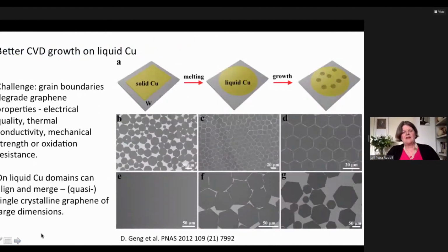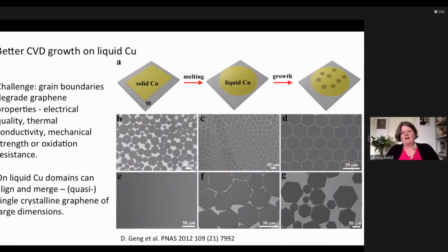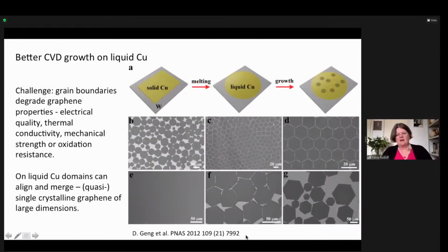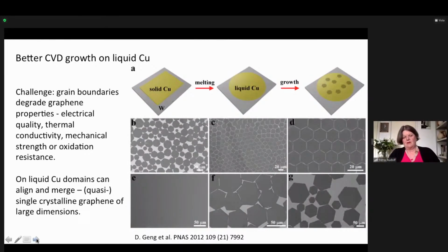So, of course, if you want to grow it for a large production, you don't do that on a copper single crystal, as I have shown you. But what people do nowadays is mainly grow on liquid copper. And when you do that, as you can see here in this example, you get islands which are perfectly oriented and merge, and you get a very beautiful quality because the domains align and they merge, so you get quasi single crystal graphene of very large dimensions.